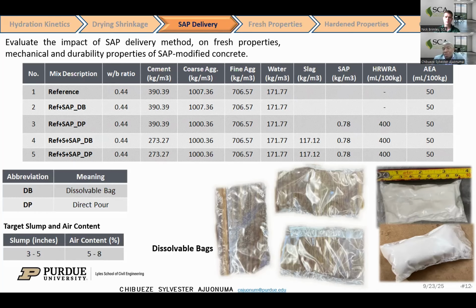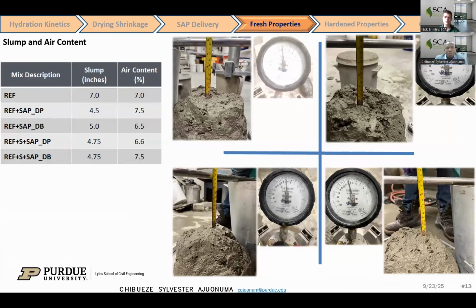And due to the volume of concrete we needed, we had to scale down the bag to a smaller scale because we needed a small quantity of the SAP at 0.7 kilogram per meter cube of concrete. So we scaled down the bag, and here are some of the results we obtained from the laboratory experiments.